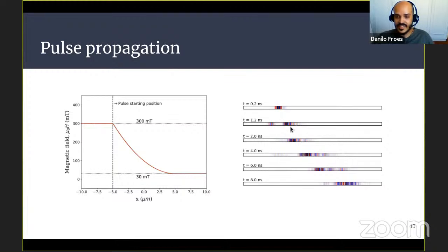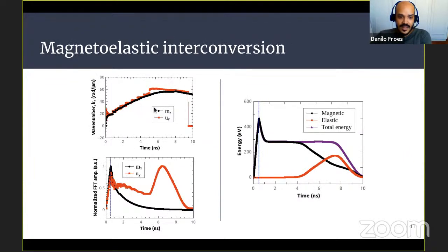Two wave fronts are formed. The left-going one is readily absorbed. The right-going one propagates and varies the magnetic field. As you can see here, other pulses, other peaks appear, until it is absorbed on the right-hand side. As you can see here, the wave number variation of the magnetization is very continuous. The elastic one has a sudden jump here, which corresponds to the point at which you get to the elastic. Here it is pure magnetic, and we have a very small intensity.